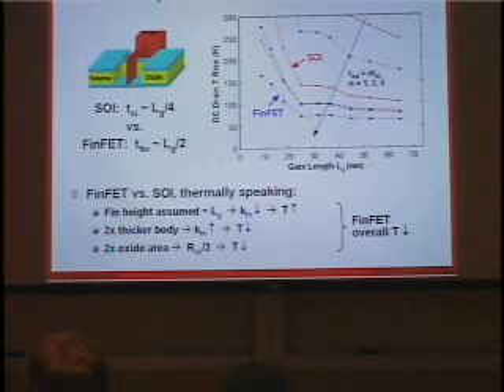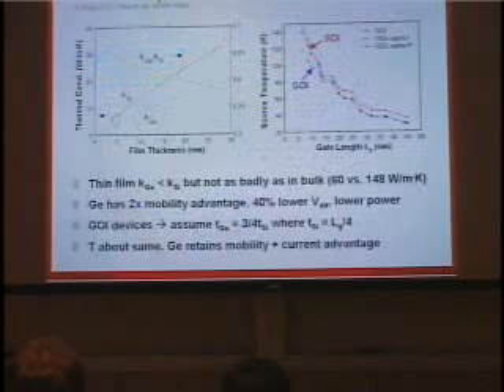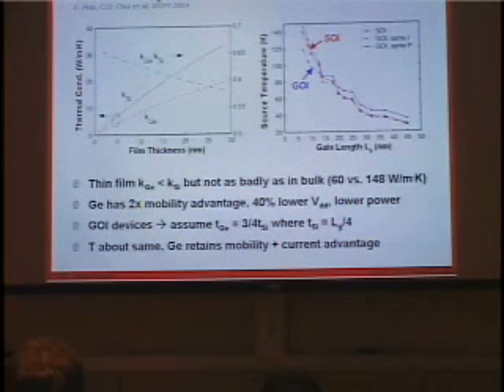However, the fact that you have a twice thicker body and a twice thicker oxide area both lead to an increase in thermal conductivity and also a decrease in the oxide thermal resistance. And overall, as it turns out, when we put everything in at the same time, the FinFETs, for the same current power, same kind of assumptions, should have lower temperatures than SOI devices. Let's do a quick comparison also with germanium-on-insulator devices.